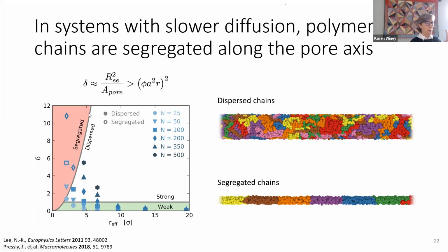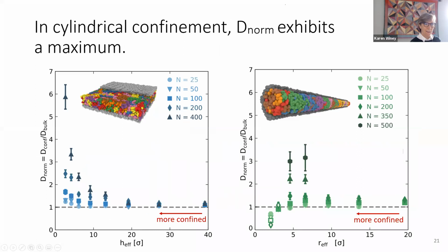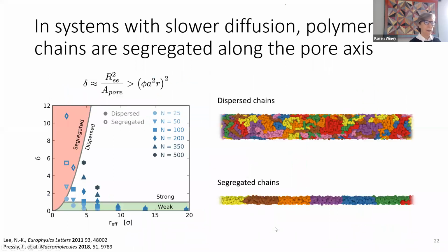And then this curve here has this dependence, where this is the Kuhn step length and this is the density of polymer. So this really just goes as R squared, where R is this confinement parameter. You can see that curve here. The symbols that are open are the ones where, in our simulations, we found the chains to be segregated. If you look closely, these open symbols are the segregated ones. So now we understand that this increase in diffusion coefficient is the loss of entanglement, until it gets so confined that it segregates.